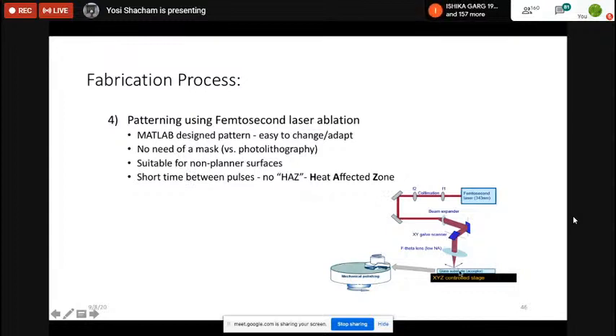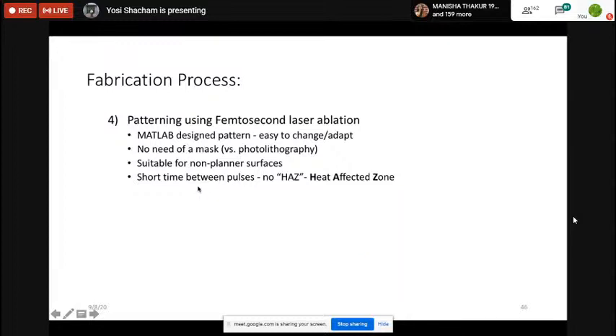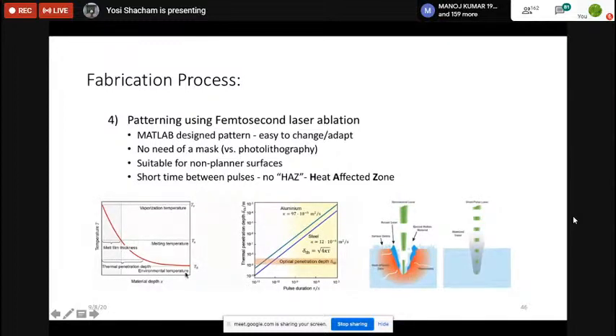Then you have a substrate with gold on titanium on the polymer, and the laser beam is ablating the metal. And the nice thing is the following. At these wavelengths, the PDMS is transparent, but the gold is absorbing. So we can pattern, and because it's a femtosecond, there is no heat diffusion. The pulses are very short, as I told you, about 270 femtoseconds. Because the time is so short, we have a huge energy density per unit area. The ablation is so fast that the rest of the substrate does not heat, and because of that, we don't have damage to the polymer under it. I'm going to show you the structures later.